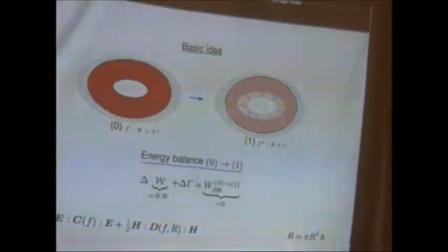We envisage that we have here the evolution of microcracks starting from the surface of the void. This implies a degradation of a certain part of the material. This way we come from this state 0 to a state 1. And this initiation and growing of microcracks requires work. This work or energy is taken from the strain energy of the volume element. So we can write down the energy balance, taking into account now for the capacity to withstand load, not the original void anymore, but a bigger void. That's the basic idea.